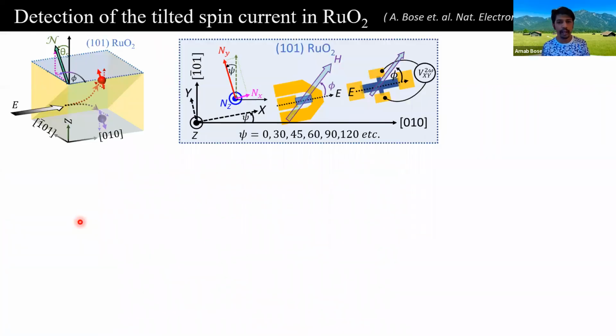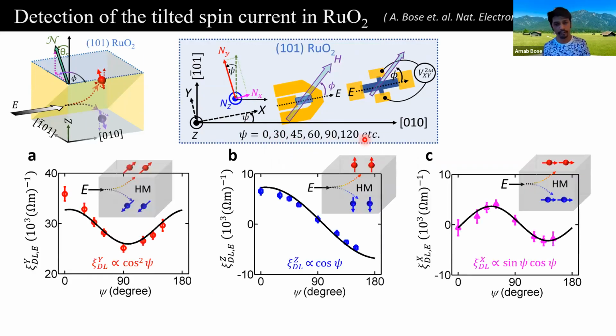Now, instead of doing only these two angles, we measured spin orbit torques for other angles, 30, 45, 60, 90, and so on. Let me show you the data for that. Here, we quantify the damping like torque efficiency for the Y polarized spin. This is for the Z polarized spin, and this is for the X polarized spin. For the Y polarized spin, the damping like torque is proportional to cos square psi. For the Z polarized spins, it is proportional to cos psi, and for the X polarized spin, it is proportional to sin 2 psi. This is a very good agreement with the theoretical predictions that I discussed before.